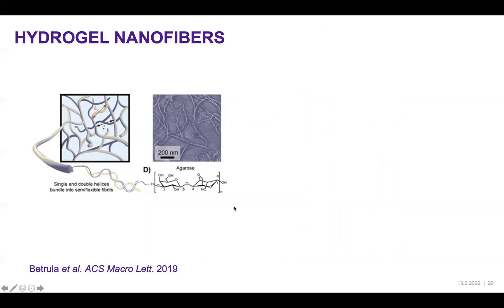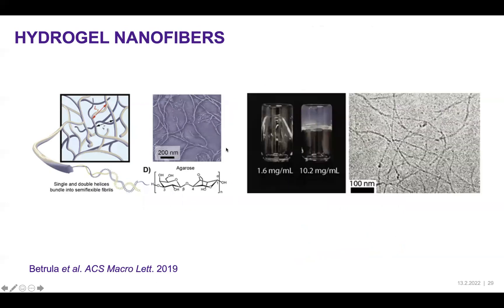It is also important that we can study various other nanostructures, such as nanofibers from gels. Here is an AFM image of a gel fiber from agarose, which is routinely used in food and other applications. In AFM you must dry the sample and then see small fibers bundled together. In cryo-TEM of this gel, we can see individual fibers of four to five nanometers in diameter but indefinite length, preventing any kind of bundling or entanglement.